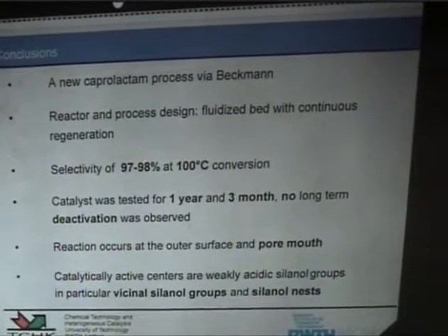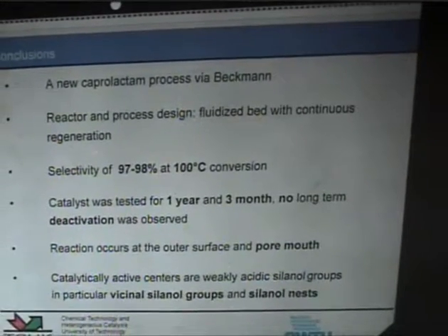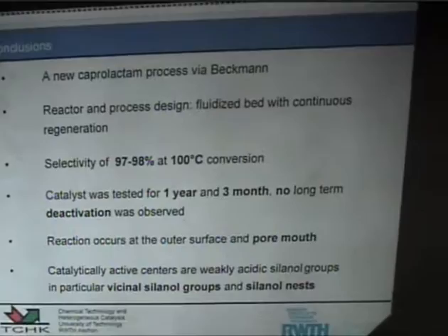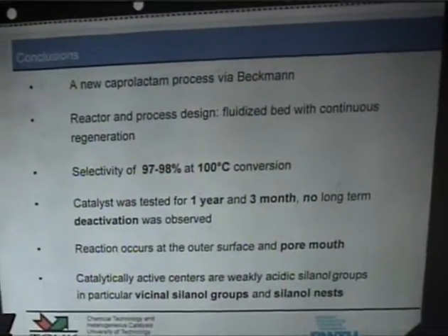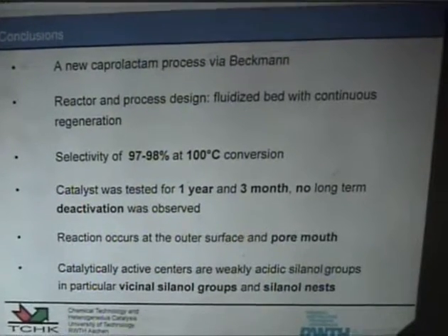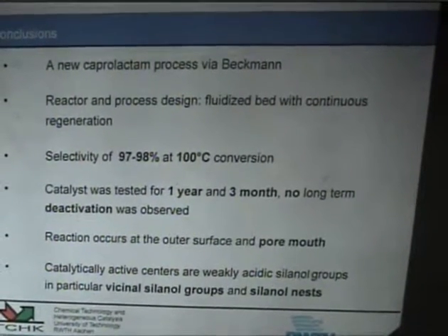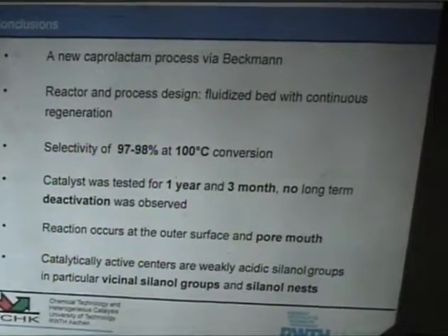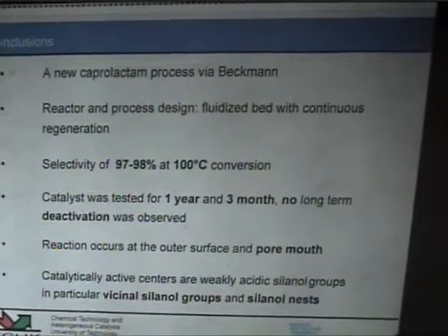The selectivity we obtain in this fluidized bed with continuous regeneration is 97 to 98% at 100% conversion. We tested the catalyst for 1 year and 3 months and couldn't observe any long-term deactivation. Furthermore, we have done a lot of characterization work, and we studied the catalyst very extensively.